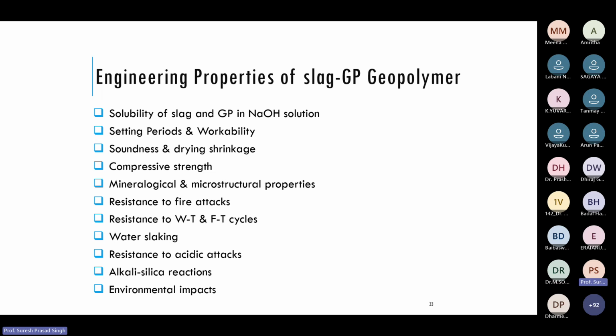So first you go for the solubility, then study the fresh properties like setting period and soundness, then the hardened properties, compressive strength, mineralogical study, and then the durability. In the durability, we studied the resistance to fire attack. As I told you, if you use soda lime glass, the residual strength after exposure to fire will be high, because it will retain the strength even though it is exposed to high temperature. That is one of the major things we got here.